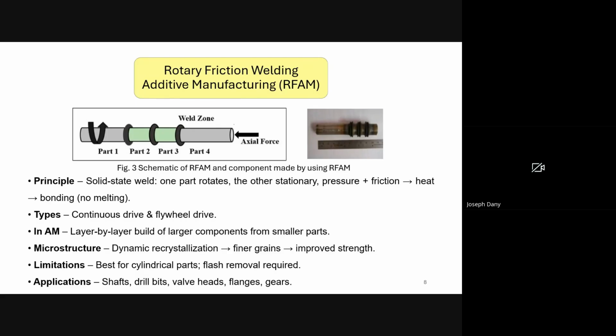Things like the spinning speed, how hard the parts are pressed together, and how long they stay in contact all influence how strong the weld is and how the microstructure looks. For example, there was an application where stainless steel layers were joined to build a thick cylindrical component. The bond between layers was excellent. The weld zone showed a finer microstructure because of the dynamic recrystallization during solid state additive manufacturing, which actually improves the strength compared to the original metal.